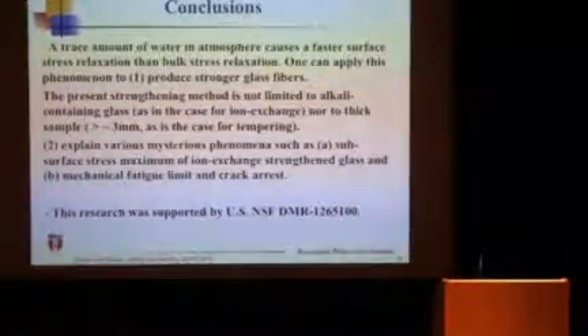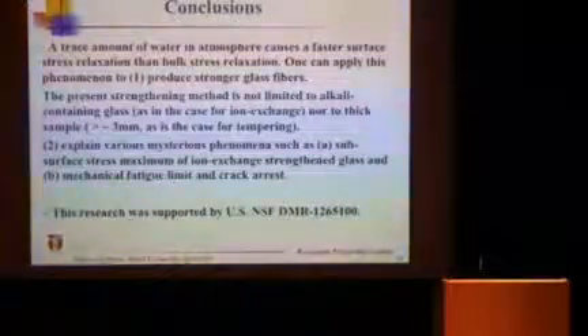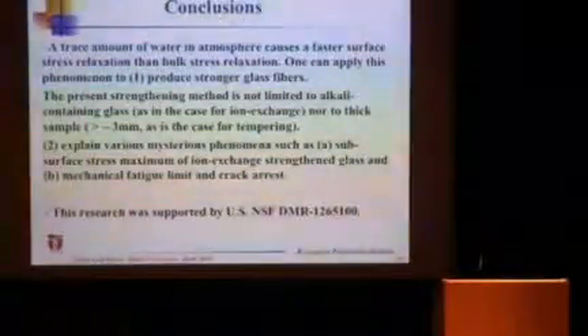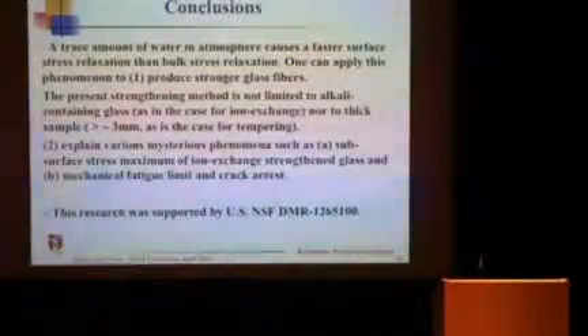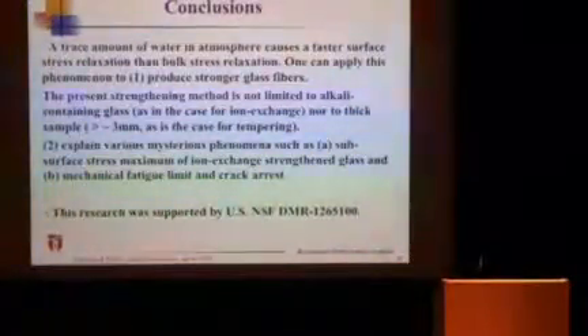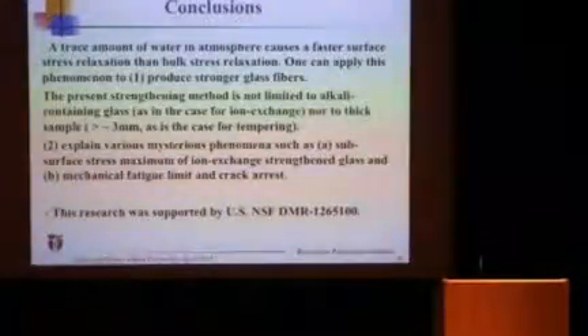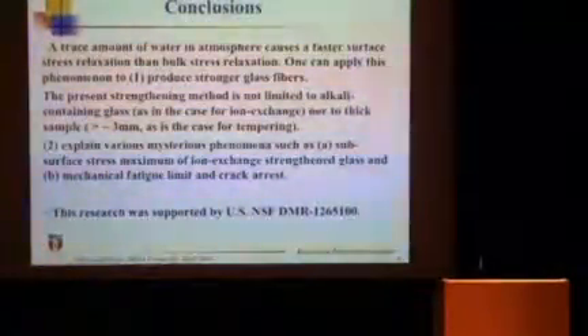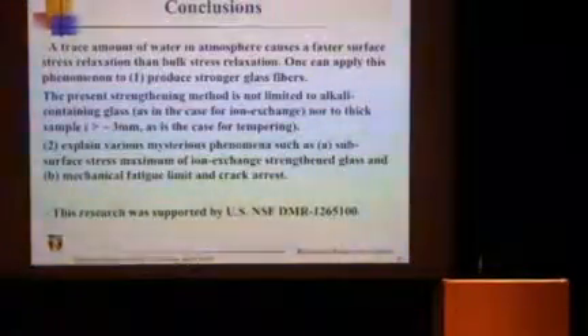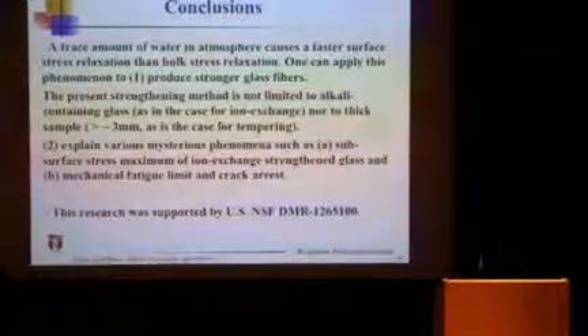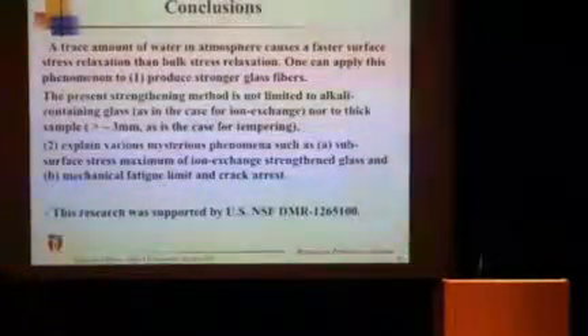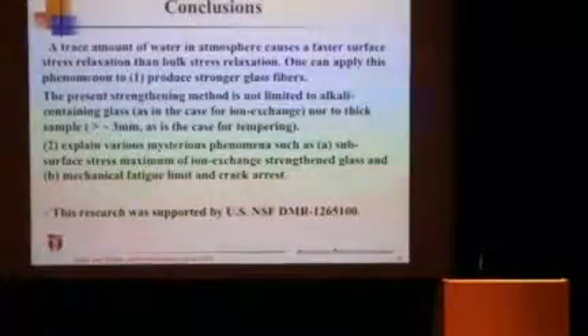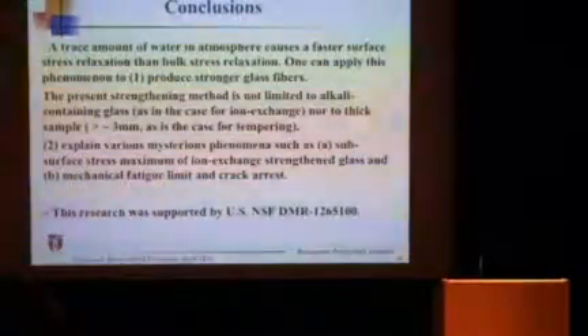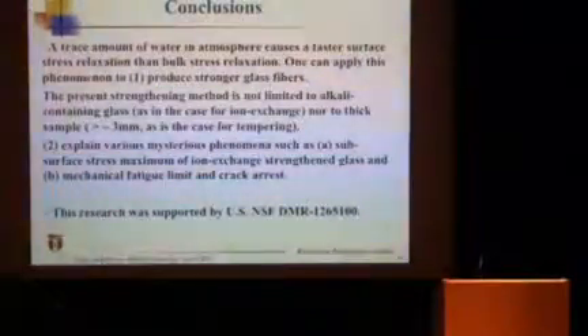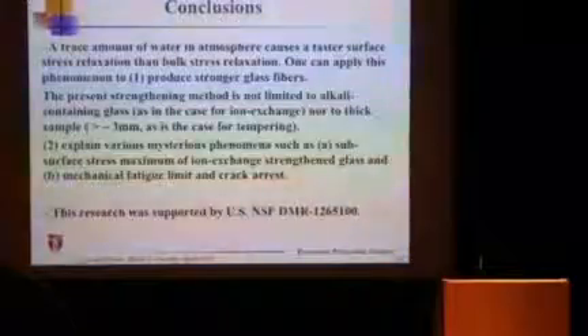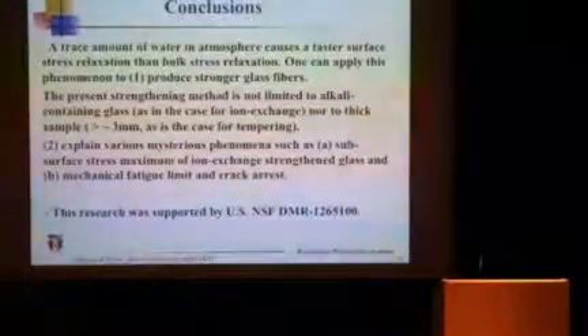As I was saying at the end, it all depends on how strong a machine you have. Even if you have a 5 millimeter rod, as long as you can pull the bar below the maximum breaking strength, you can go as high as the glass bears, or even bending. And that much of applied stress approximately has added up as a compressive stress. In principle, we haven't demonstrated a large bar, but in my opinion, even sheet glass from Corning, maybe put two-dimensionally, make longer. So I think all the limitation is your imagination.